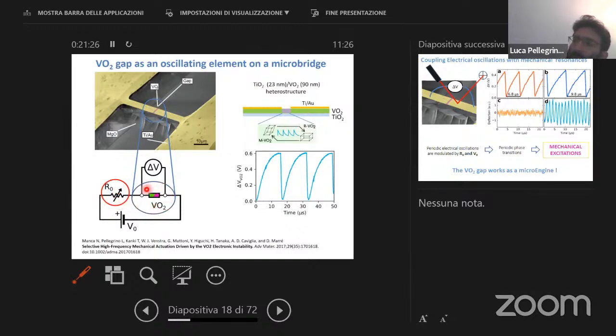I will not go into detail, but what happens is that these systems go to metallic and then go back to the insulating state, and you have this kind of oscillating behavior due to the instability of this and the energy that comes from the DC voltage. So this becomes metallic. Once it becomes metallic, you get less energy due to Joule effect. Then it cools down again and becomes insulating. And then in the insulating state, it heats up due to the current by Joule effect, and goes back to the metallic state. And again, in the metallic state, the Joule effect is lower because the resistance is lower. For the same current, you have less energy, so that you go back to the insulating state. So you have some kind of electrical oscillation that depends on the amount of voltage and on the amount of the resistance you place in series with this device.